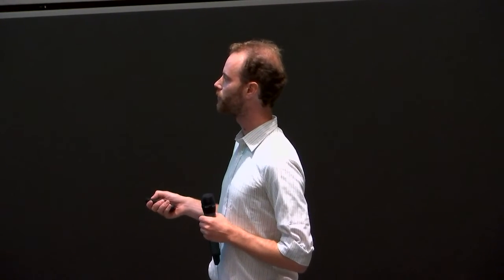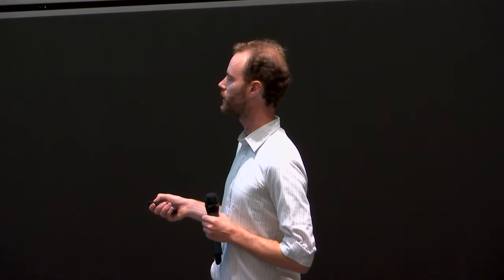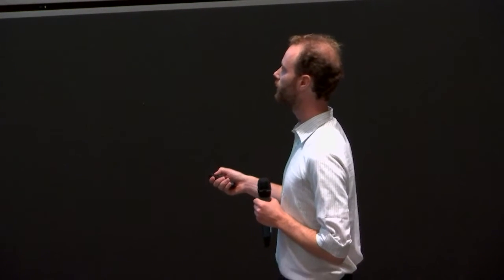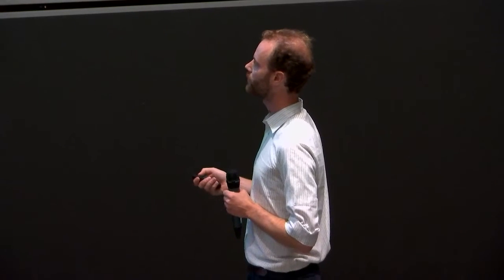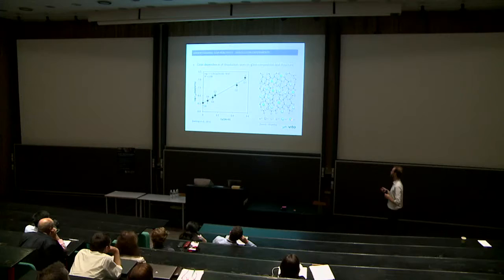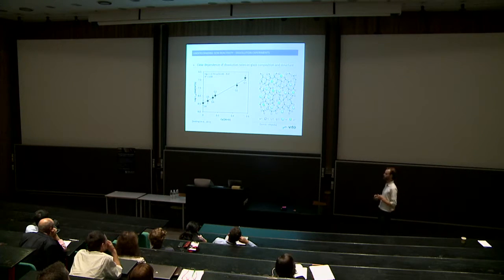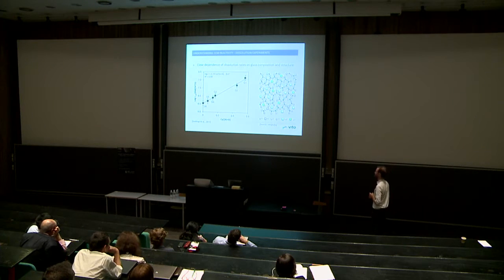So where is this coming from, this dependence on, for instance, the calcium to aluminum plus silicon ratio? This is a picture of a glass structure here, and you can see that when you enter more of these sodium or potassium ions in the structure, you break up bonds between the silica tetrahedra, the silica and aluminum tetrahedra here. And the more depolymerized the structure is, the more liable to dissolution it will be.